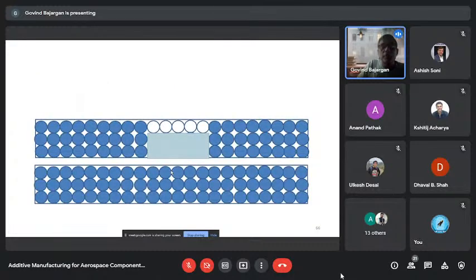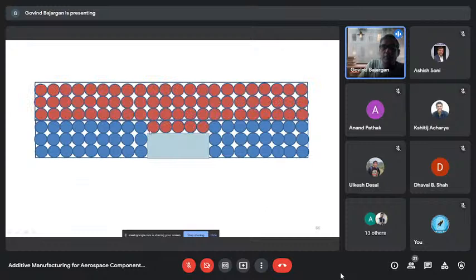Just to understand how much energy is required for melting for a given layer thickness, and how to estimate that, I have made a small graphic presentation. Assume that the three circles here, this whole thing, represent a single layer thickness. Suppose the laser has passed and melted a particular zone. When we melt, we form a dense part, so it leaves a gap here. There is nothing here now. We have liquid metal which has solidified, and there's powder. There is nothing here. So when the next layer comes in, powder comes here also.